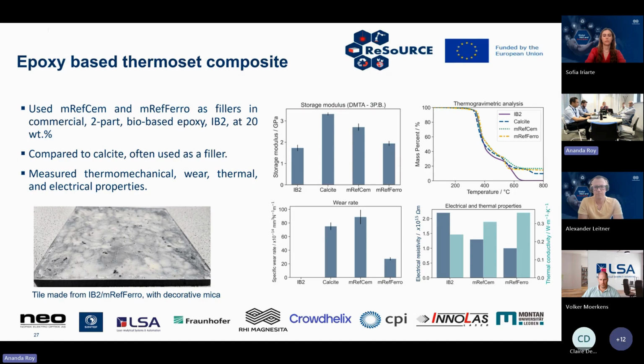So firstly, we would like to start with the epoxy-based thermoset composite. So looking into the thermoset functionality of these fillers within the epoxy composites, especially looking into their thermomechanical, wear, thermal and electrical properties. As you can see with this slide, the enhancement, especially in the storage modulus, is quite a bit higher in terms of the calcite on the first graph within the storage modulus. And it outperforms both the untreated and surface treated MREF-based fillers. But the advantage of this impressiveness is application based, depending on what is required within the thermoset context.